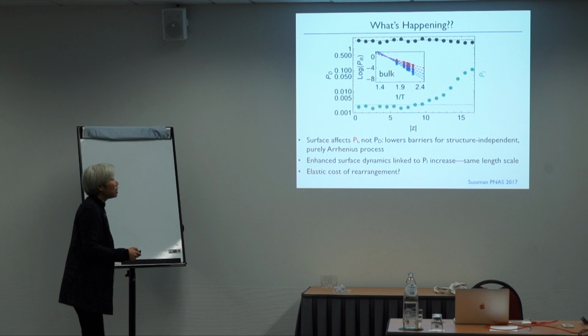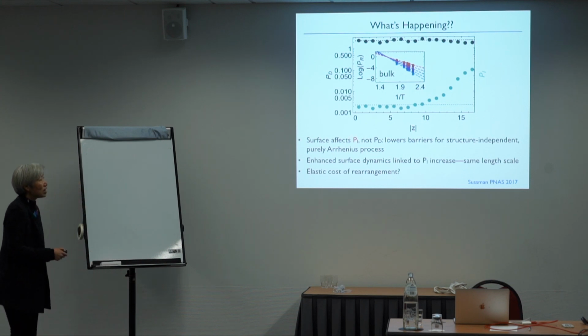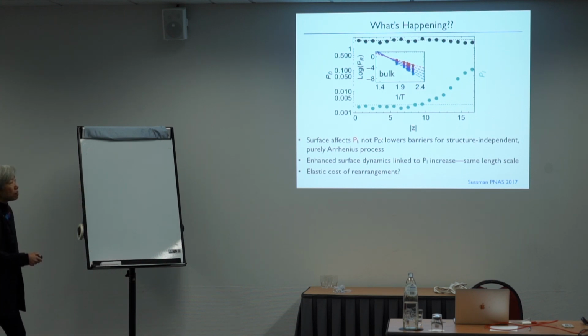So it says the surface is affecting the structure-independent piece, not the structure, and it's lowering the barriers for the structure-independent, purely Arrhenius process. That's actually consistent with the experiment. That's been established by the experiments, that it's a purely Arrhenius process that is speeding things up at the surface.